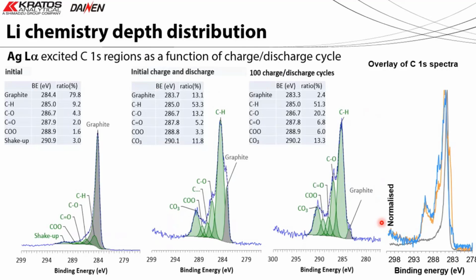Again, if we look at the carbon 1s in a bit more detail, we can see a very strong graphitic asymmetric component. But again, on the as produced sample, there is already some degradation product associated with the anode material. Increasing the charge discharge cycles, we see attenuation of the graphitic carbon anode, and an increase in the organic and carbonate species.